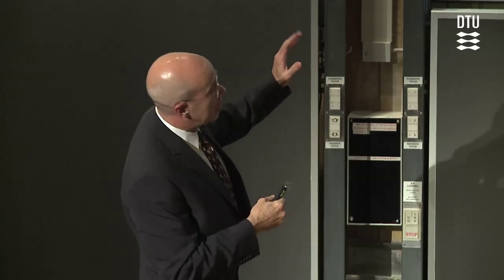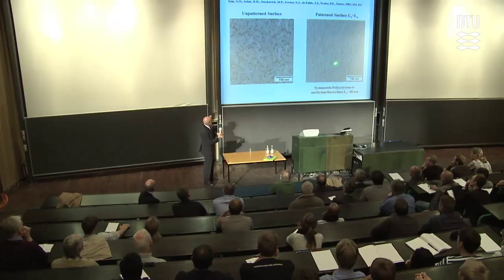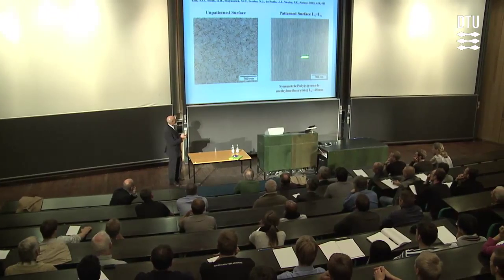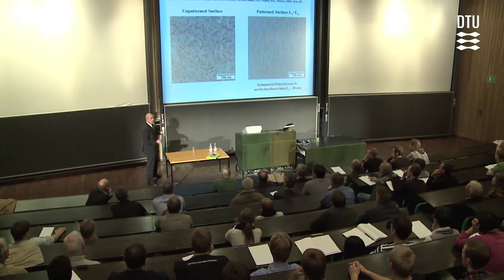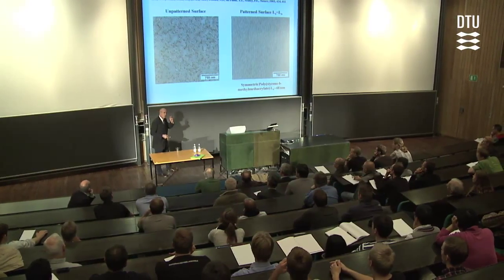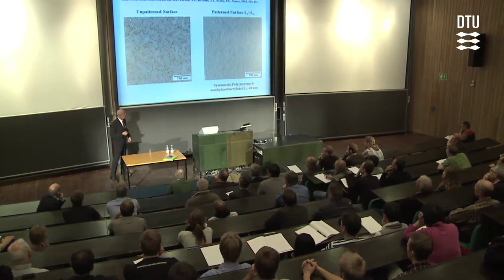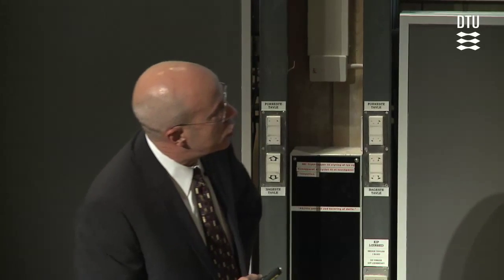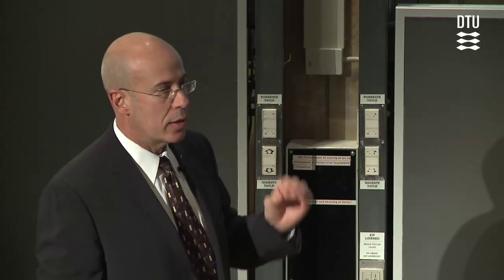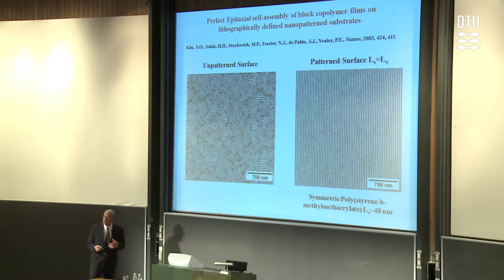The moment you self-assemble exactly the same material on a surface that has lines on it, you get these beautiful structures. So this was a surprise to us for 2 reasons. The first one was that you could do it at all. We were ready to give up on this process. More importantly, you see that you don't have a single defect, not one mistake, over relatively large areas. And that was a surprise. We thought it would work, but not as well.